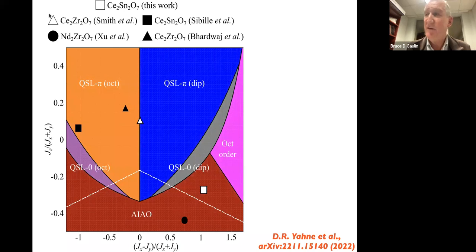But the other thing is that the theoretical calculation that's been done has been done for this nearest neighbor only XYZ model, right? And so you get the best description compared to that. According to that, you've got this transition to an all-in, all-out Néel state at sufficiently low temperatures. But if you added in perturbations beyond this simple XYZ Hamiltonian, well, this is a pretty weak phase transition, so it's going to be knocked around pretty easily by perturbations.